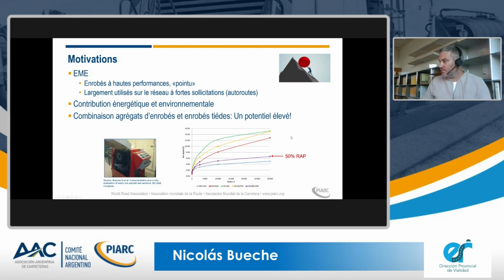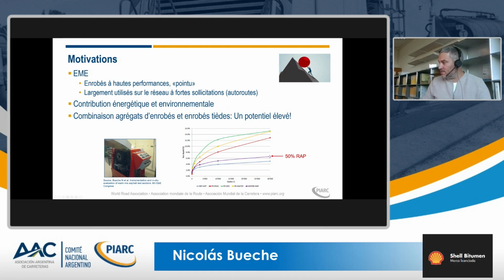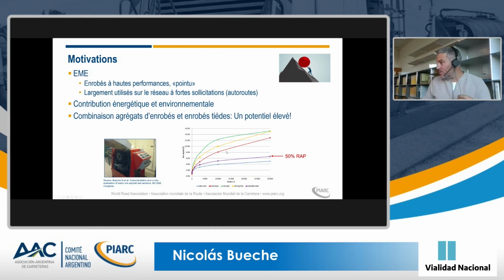And the figure you can see on the right hand side, this curve here, the 50% RAP, is a foaming technology. And if we take the same mixture without RAP, it will be, in that case, the yellow curve, which demonstrates that adding RAP is not always negative. In that case, it was a specific test. By adding RAP, we get even less rutting for the asphalt.